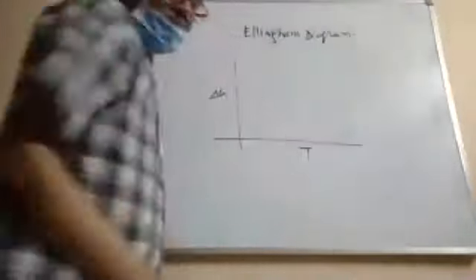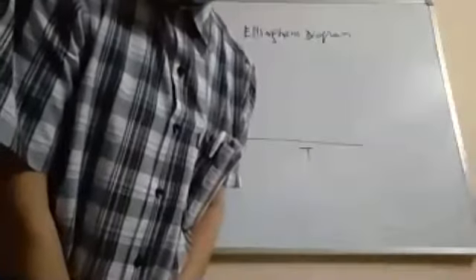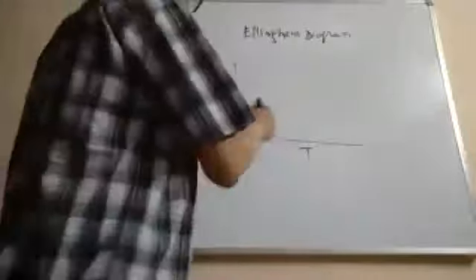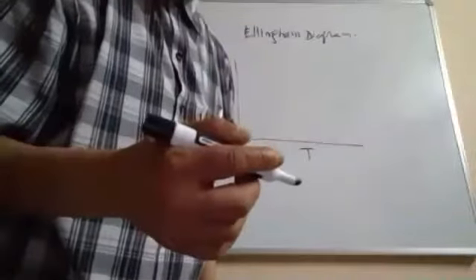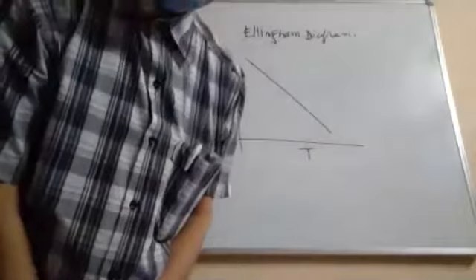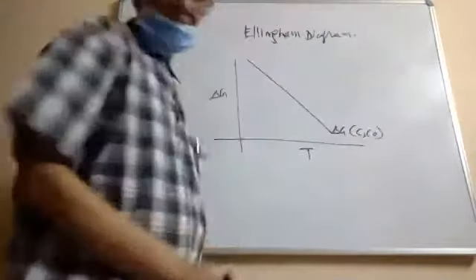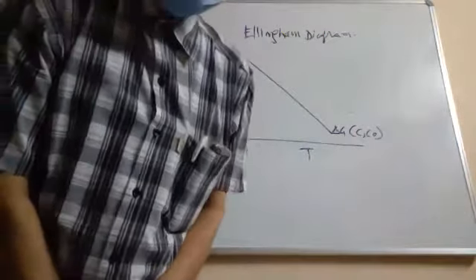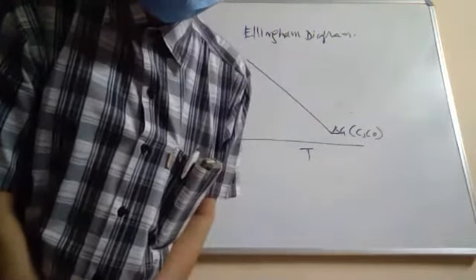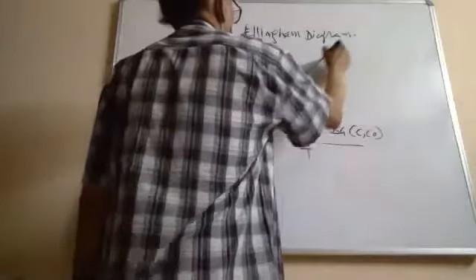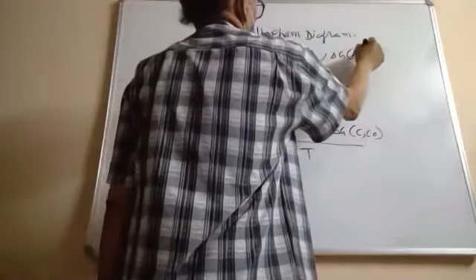So let's see how that looks like. These are extremely important in metallurgical processes. So what you're plotting now here is delta G as a function of temperature. We all just agreed a minute ago that in the case of oxidation of carbon to carbon monoxide, because delta S is positive, the delta G will decrease as you increase the temperature. That's the kind of line that you see. So this is for the delta G of carbon monoxide. Now, if you were to do the same plot for the metal getting oxidized, it will go like this. That will be the delta G for the metal to metal oxide.